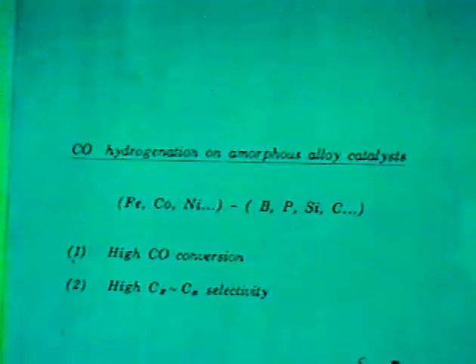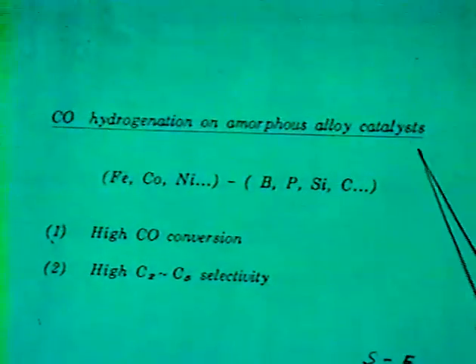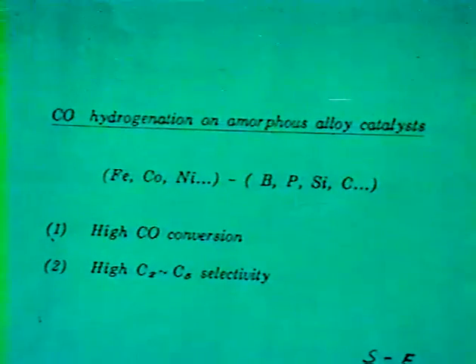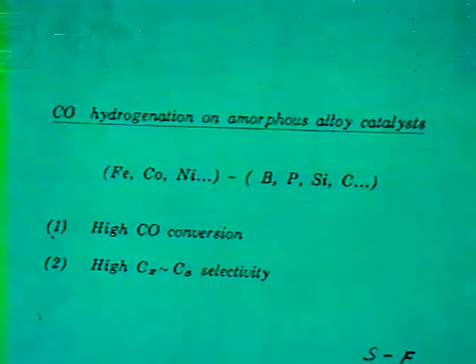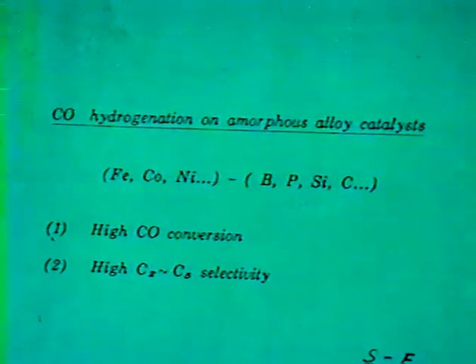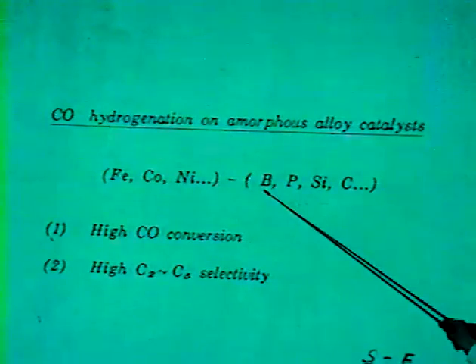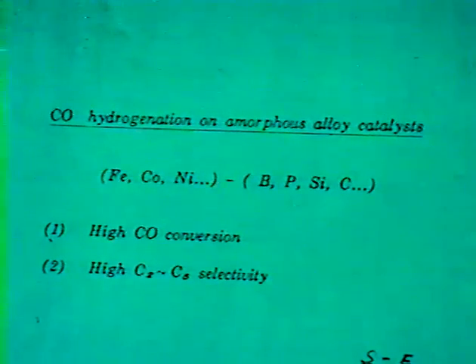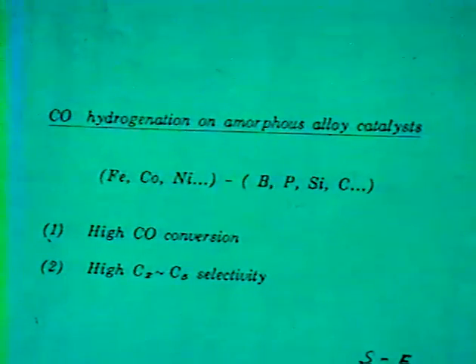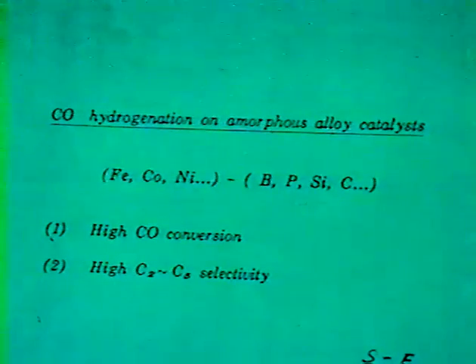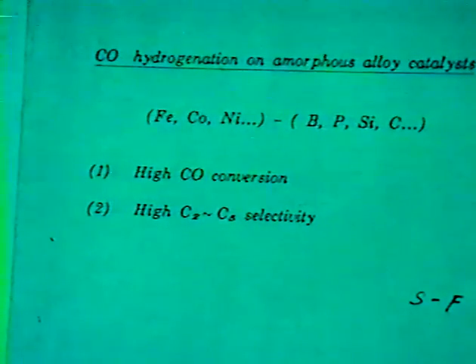Some authors have studied these amorphous alloys as catalysts for CO hydrogenation. The experimental results indicate that almost all these amorphous structures have higher CO conversion and higher C2 selectivity than their crystalline alloys. In addition, for some of the amorphous catalysts, the reaction product distribution does not obey the Schulz-Flory distribution. These unusual catalytic properties are interesting in the field of C1 chemistry.